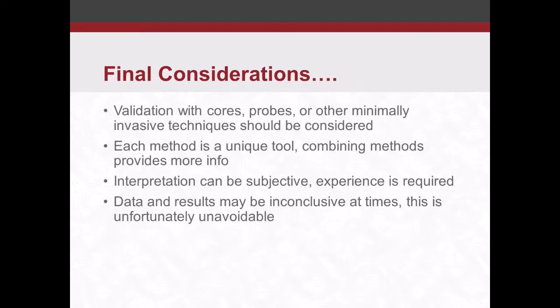So that's all the case studies we've got. A couple of final considerations. Validating some of the data with cores or probes or some other minimally invasive technique. Again, this depends on the purpose of what you're doing. On that initial project that I talked about where we used ultrasonic pulse velocity, we did take some cores, we drilled some probes, we did some chipping, so we were able to validate some of our data there.